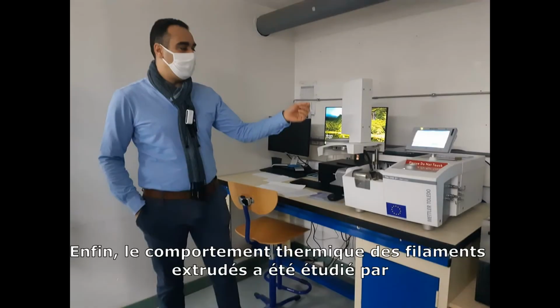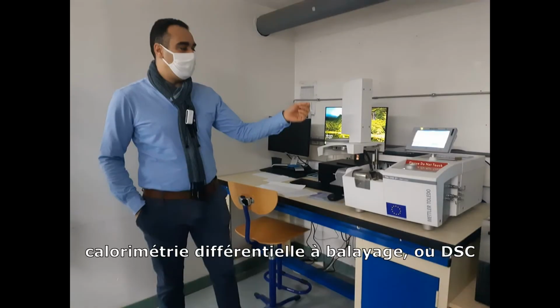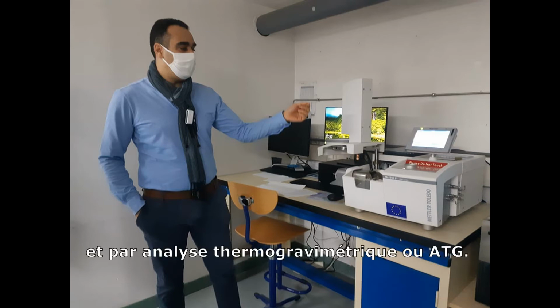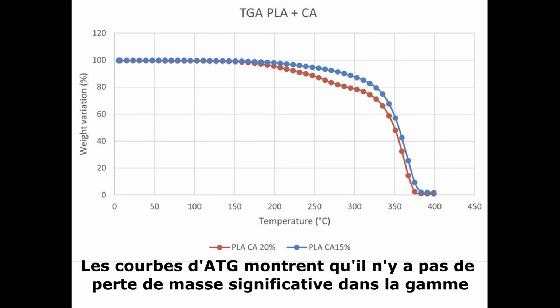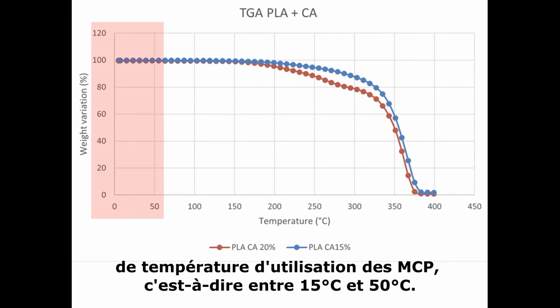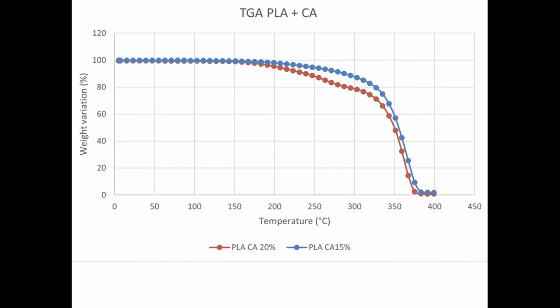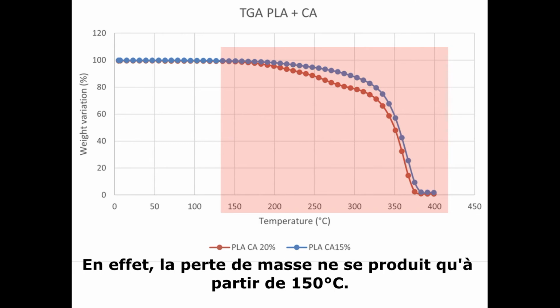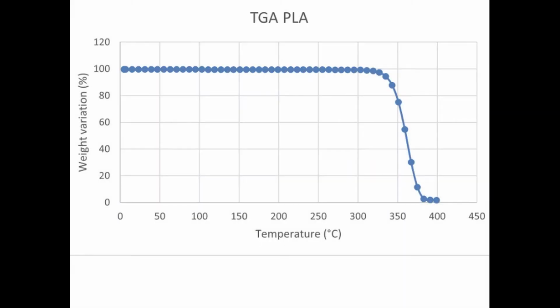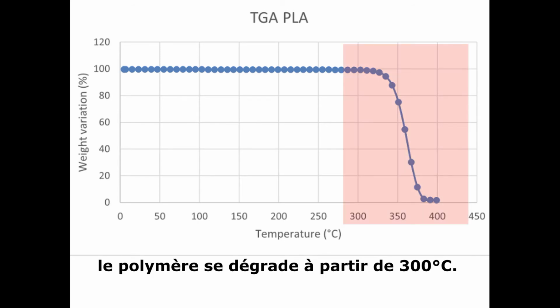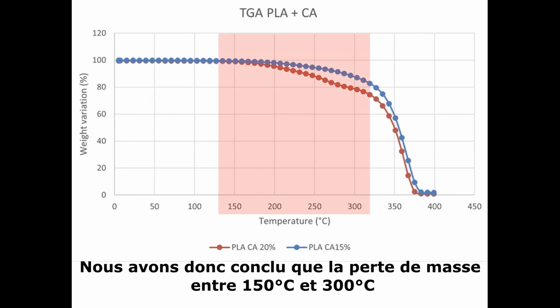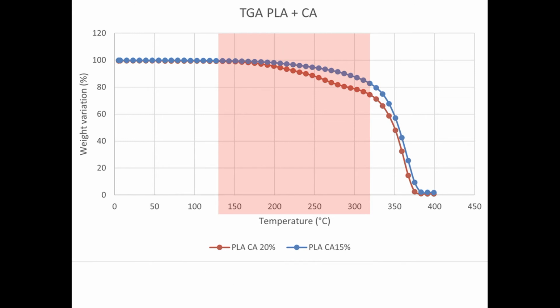Finally, thermal behavior of the extruded filaments was studied by differential scanning calorimetry, or DSC, and by thermogravimetric analysis, or TGA. The TGA curves show that there is no significant weight loss in the PCM's temperature range of use, that is to say between 15 and 50 degrees Celsius. Indeed, weight loss happens only from 150 degrees and up. By comparison with the PLA curve, the polymer is degrading from 300 degrees. We conclude that the weight loss between 150 and 300 degrees is due to the degradation of the PCMs.